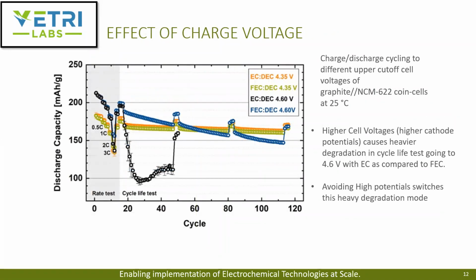This was just to show on a coin cell, not looking at a true cathode potential, but just going to a cell voltage of 4.6 volts versus comparing to 4.35 volts. Both systems, ethylene carbonate and the fluorinated ethylene carbonate, you can see if you don't go to higher potential, you don't get into the capacity fade, which clearly indicates that the degradation modes are associated with electrode decomposition first, and then later associated with the interaction of the electrode with the electrolyte further.